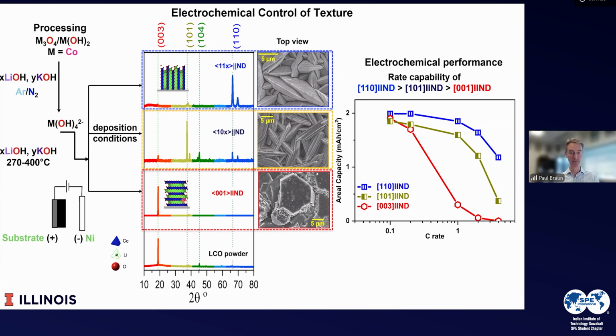Now, from a rate performance standpoint, the vertical orientation is much preferred, because the fast ion and fast electron transport directions are parallel to the 003 planes. There may be reasons you want to go to various angles, and I'll discuss that briefly because it allows control of the chemomechanics, which is very important for solid-state batteries. But unlike a powder, where it is randomly oriented, here we can control it.